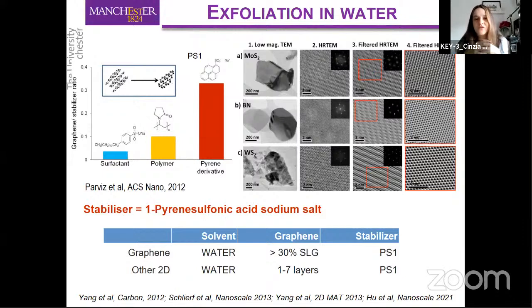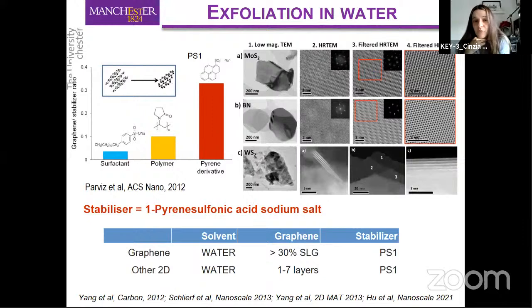And in addition to this work, we also demonstrated that exfoliation with pyrene derivatives, and in particular with PS1, is possible, and the quality of the material produced is extremely high. You can see that we don't have any defects. And in the case of graphene, we don't have any carbon-oxygen formation. So although we work with water, this material has nothing to do with graphene oxide or reduced graphene oxide. And the approach can be used to exfoliate basically any layered material that is not reactive in water. So we can use it to exfoliate transition metal dichalcogenides, boron nitride, and so on. And the flakes are really thin. Typically the average number of layers will be between 3 and 7, as you can see from the TEM pictures, with obviously a smaller amount of single layers and bilayers.